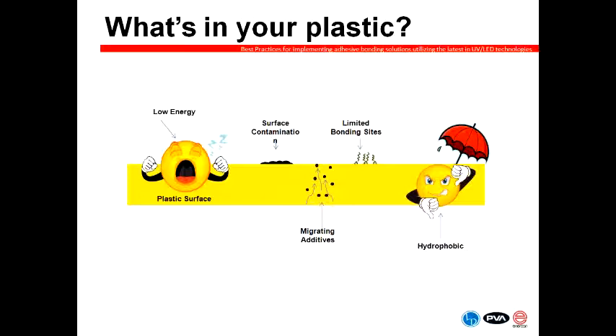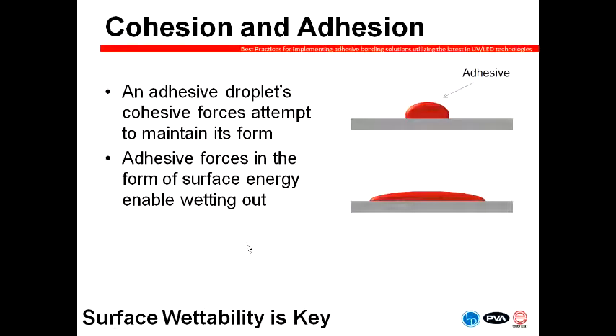Sometimes one of our customers will run a part, treat it and bond to it one week, and then a week or 2 or 3 or 4 later they run the same part, maybe the same batch, and they're having problems. And often we'll find in those cases it's blooming additives that cause their issues. The final piece is limited bonding sites. All of these contribute to a surface being hydrophobic, or not wanting to accept an adhesive. So low energy, lack of bonding sites, and contamination all have a negative impact on adhesion.